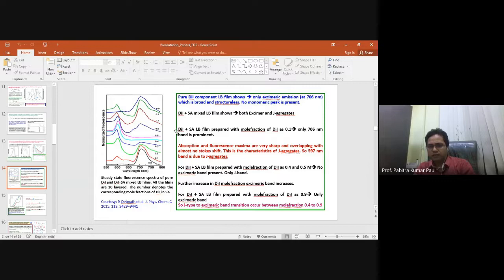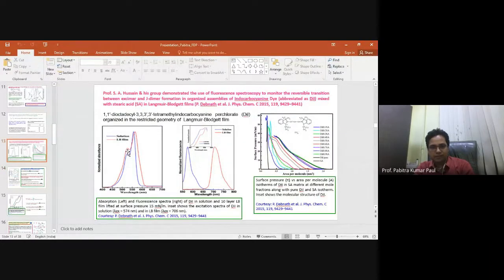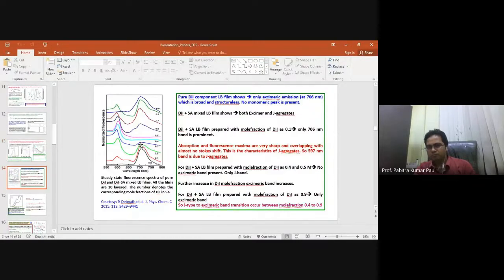So for mole fraction 0.1, only this 706 nanometer band is present, and absorption and fluorescence maxima are very sharp and almost overlapping. If I go back to the previous slide, you see there is very sharp maxima, absorption and emission, with no such shift. There is no significant shift of the absorption and emission spectrum, so the Stokes shift is very small. It is the characteristic of a J aggregate when the J aggregate band is observed.